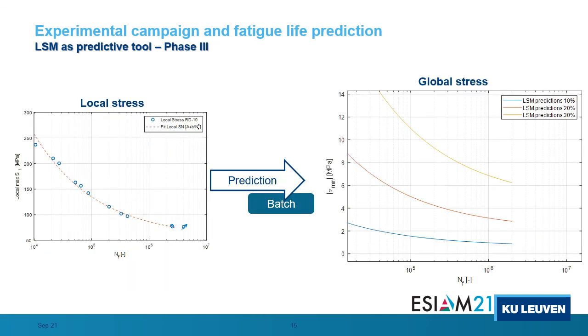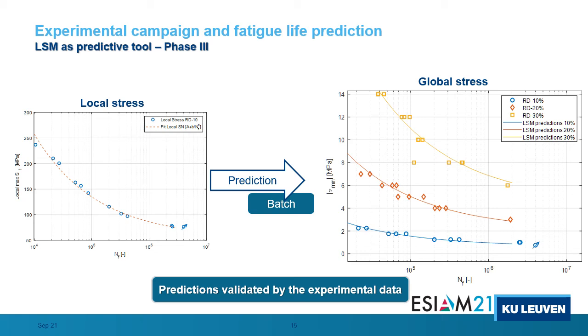The results of the prediction of the local stress approach are presented in the picture on the right side in terms of global stresses as a function of the number of cycles to failure. 3 SN curves were obtained for the 3 different batches, showing higher fatigue resistance for higher relative density. Comparing the fatigue test results with the fatigue predictions, it is possible to appreciate how well the local stress approach can estimate the fatigue life of the metal lattice structures investigated in this study. This methodology could be extended to other metal lattice structures with different unit cells and produced with different materials to extract the structural fatigue life with a limited amount of coupons, saving time and money.